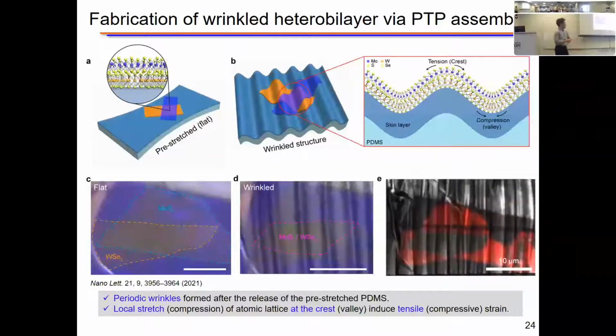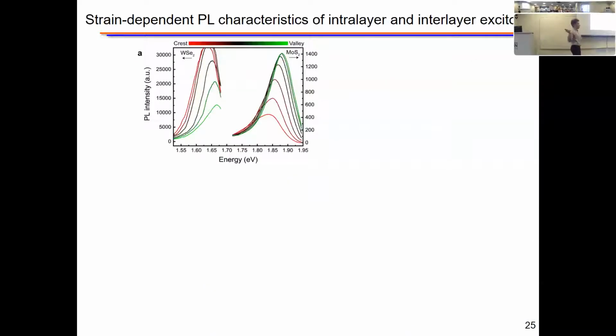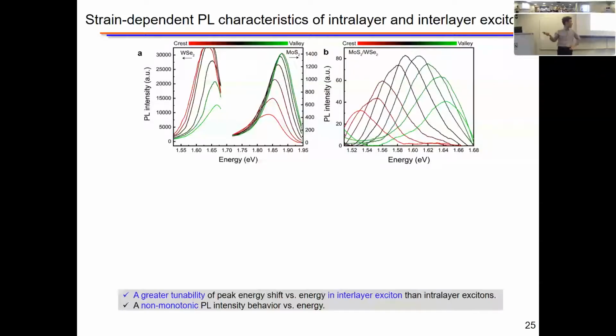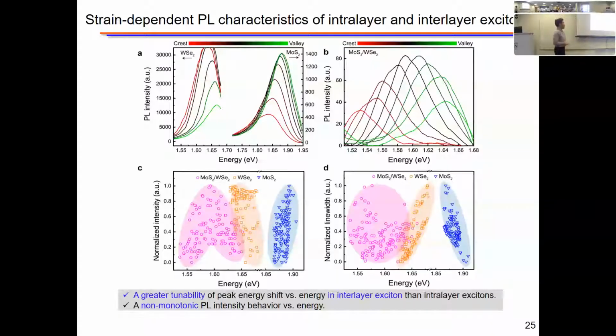After creating the wrinkle structure, we conducted confocal PL mapping, showing that there's a substantial quenching at the heterojunction, indicating that we're creating decent interlayer coupling because of the ultra-fast charge transfer phenomena in such type 2 band alignment. In order to probe the strain effect, we spatially probe the photoluminescence energy of a representative wrinkle, including both intralayer and interlayer exciton. I'll just move on to the interlayer exciton because this is the more common phenomenon in the articles.